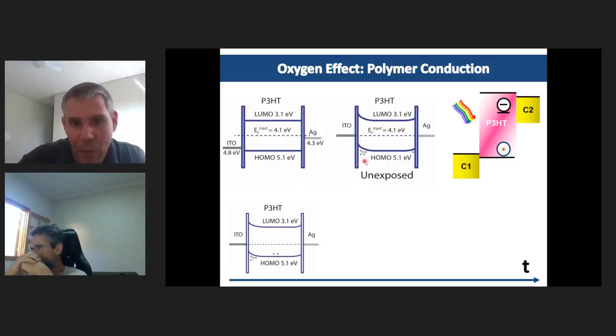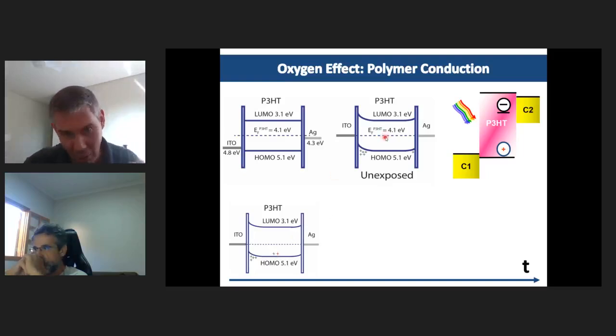And the reason is, well, now we understand that for the unexposed device, I have this big reservoir at the interface. And as I start exposing my devices to the oxygen, remember that I create this oxygen trap, and then I start p-doping the P3HT. And by p-doping the P3HT, I add positive charge holes into the material. And when I do so, in terms of the energy level, I'm pulling the energy level towards the HOMO of the material. So the energy level that before neutral was 4.1 electron volt, now is moving towards the HOMO of the material.